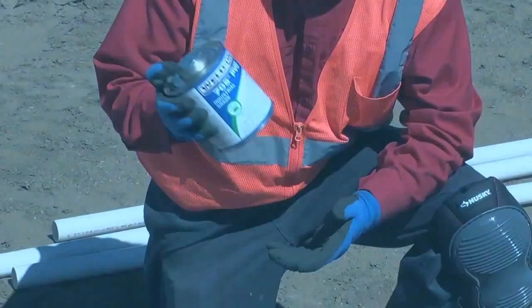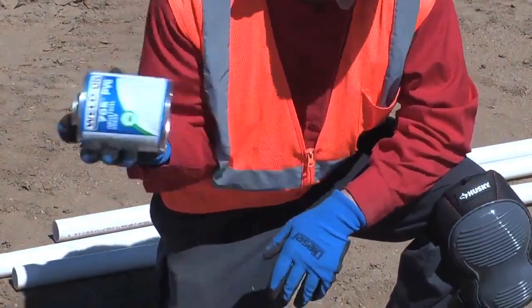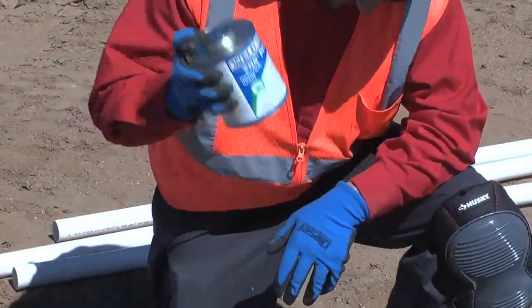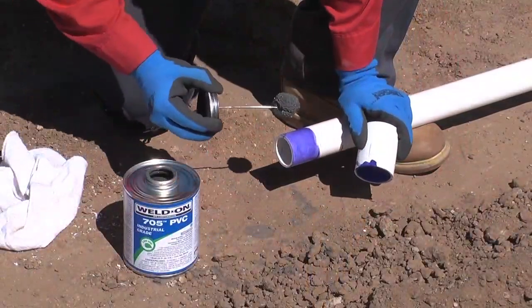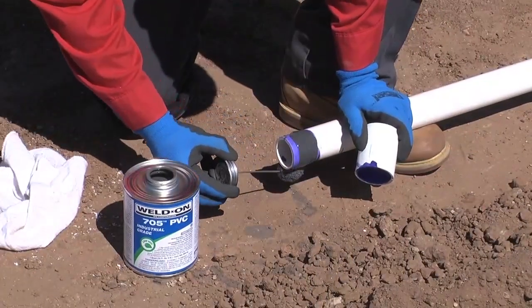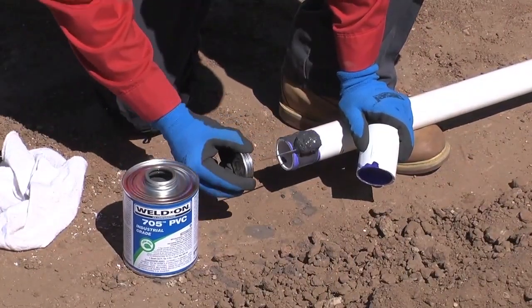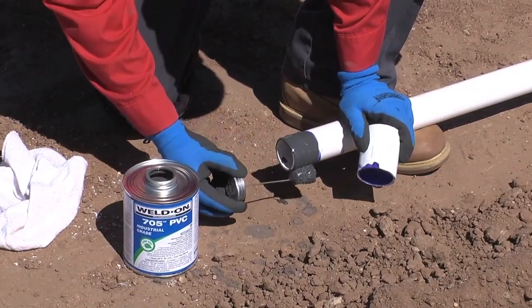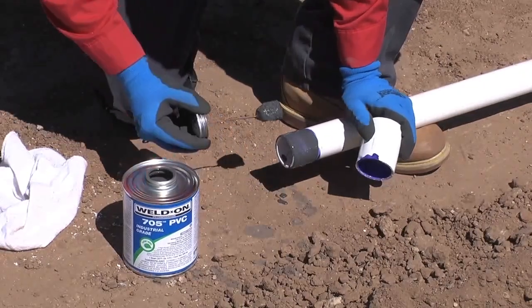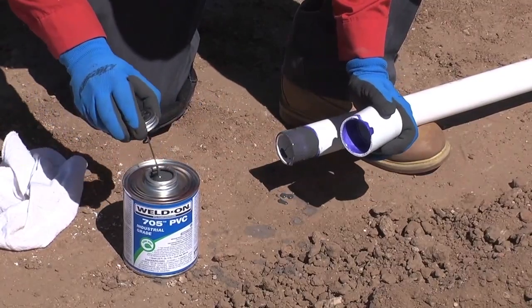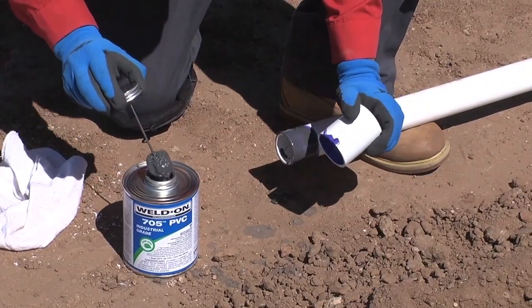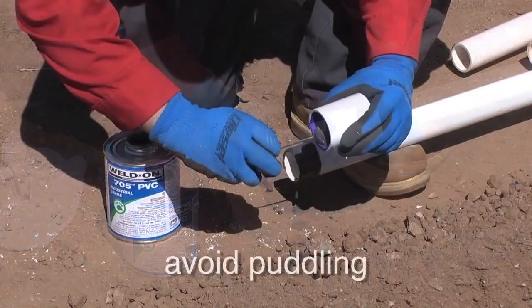Shake the can of solvent cement thoroughly before use. While joining surfaces are still wet from primer application, immediately apply the appropriate Weld-On solvent cement in a full, even layer onto the pipe outside diameter, equal to the depth of the fitting socket. Apply a medium layer of solvent cement to the fitting socket. Avoid puddling.